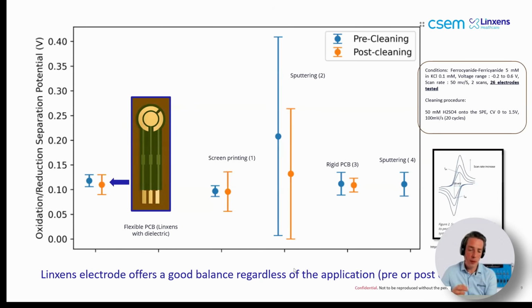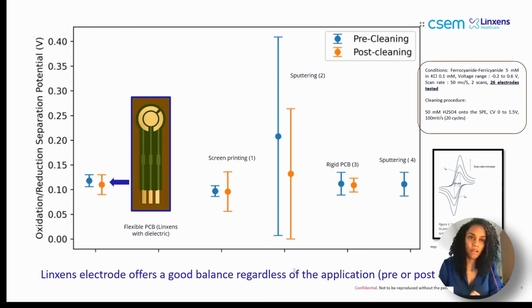Exactly. And when nickel is being used as this intermediate layer, can it become accessible if you bend the Linxens electrode? Would you be able to see it? No, you can't, because at the end, the electrodeposition of the gold will be done on all the surface of all the conductive surface that you will have. The gold will be deposited, so you will not see it.